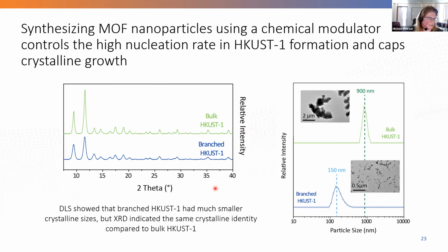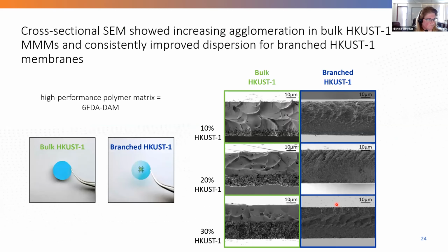What we see in the XRD is that there is no difference in the crystalline identity between bulk and branched MOF materials. But when you look at the particle size on the right-hand side, you notice that the bulk materials are about 900 nanometers. By using these chemical modulators and capping the crystalline growth, we're able to achieve much smaller overall MOF particles. They're also branched in morphology, which is very interesting.